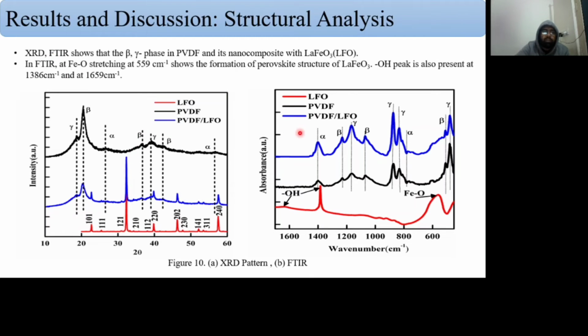With the help of these figures, XRD and FTIR, we can see here that beta phase in PVDF is formed along with gamma and alpha phase, but beta and gamma phases are dominating. So we can see that our film is actually polar, and the XRD pattern of the lanthanum iron oxide shows the perovskite structure, having an orthorhombic crystal structure. This was analyzed with the help of X'Pert HighScore and matched with the JCPDS file.